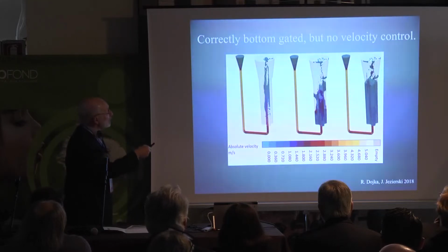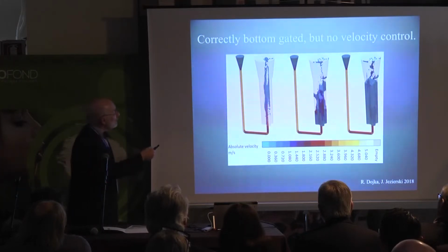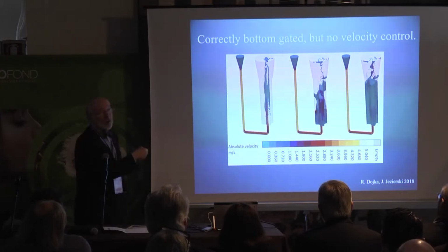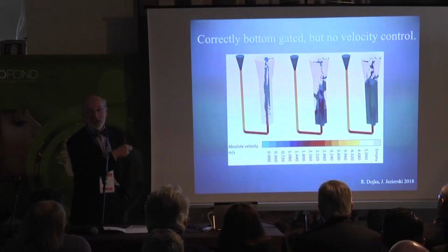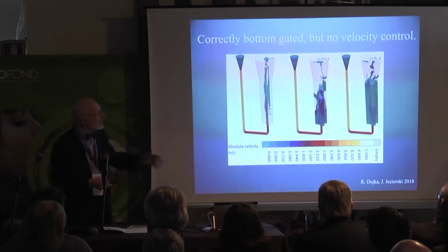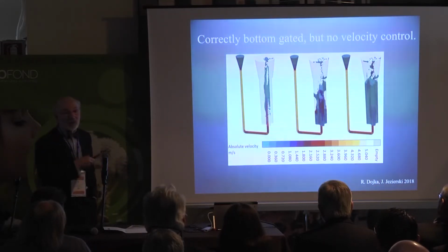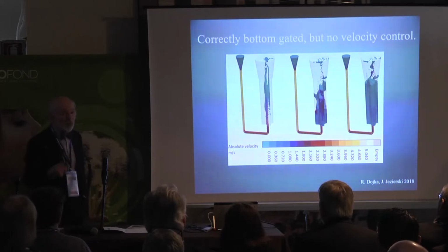And of course, this is like quicksilver. Your liquid steel or your liquid aluminium behaves like quicksilver, and so you lose almost no speed around this corner, and so it jumps the full height of the casting. And you can see this, particularly in steel foundries. You watch the metal come up and it tumbles down. And so this is a wonderful system for creating bifilms and getting the worst possible properties.